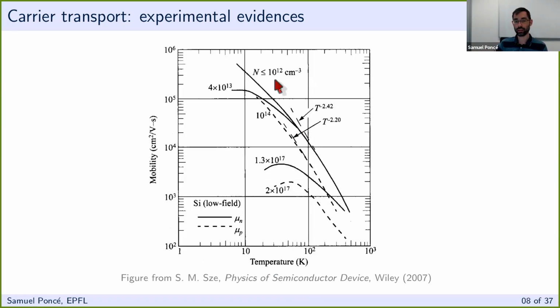Now, if you look at a fixed carrier concentration, and then you look at how the mobility changes, and those are experimental data, as you increase the temperature, you can see that the mobility is dropping because as the temperature increases, the phonons vibrate more, the atoms vibrate more, and therefore the electrons will interact more with the phonons, and therefore this will reduce the mobility by increasing the scattering. And so those are the intrinsic, very pure silicon samples, and the lines that you see here with 10 to the 17 are the ones that are much heavier doped. And you can see that the mobility is reduced and also further reduced by temperature.